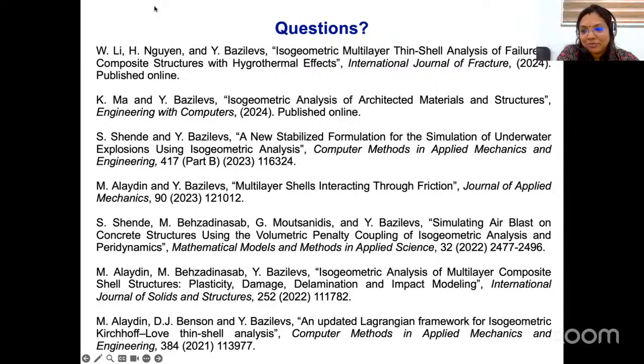We have one more question, Professor. What are the key challenges encountered in implementing the mixed mode cohesive damage model for delamination? Question from Gopika. I think the biggest challenge was to get the opening and closing under control. When your cohesive damage variable is nearly 1, so locally you have complete delamination, yet when the closure happens, you don't want interpenetration. I think developing that modified law that uses a continuous stiffness as you transition from opening to closing.